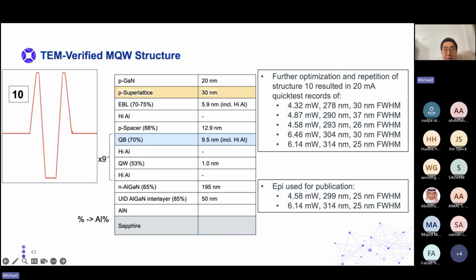And this structure is basically what is in our recently published world record LEDs. So aluminum nitride templates, and then our standard interlayer, and then 200 nanometers of n-type AlGaN. And we didn't need the n-type smoothing layer because this thinner n-type AlGaN is not as rough as the 400 nanometer material. And on top of this, with our multi-quantum well, we grow this high aluminum layer, grade up to it, then grade down and grow the quantum well, grade up to the high aluminum, and grade down and grow the quantum barrier. So the total thickness of this quantum barrier and the high aluminum layers is about 9.5 nanometers, and the quantum well is about 1 nanometer.